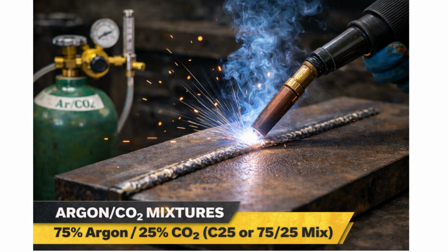Argon, CO2 mixtures. This is where most steel welding happens. The most common blend is 75% argon and 25% CO2, often called C25 or 75-25 mix. This combination gives you reduced spatter compared to pure CO2, better arc stability, smoother weld appearance, good penetration, and versatility across different materials and thicknesses. For even cleaner welds, some fabricators use 90-10 and 95-5 argon, CO2 mixes, especially for thin materials or when appearance is critical.